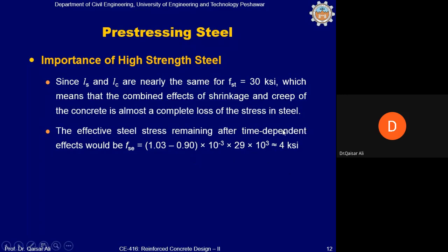तो हमें पता चल जाएगा कि हमारे पास फाइनली स्ट्रेस कितना रह गया। तो द फाइनल स्ट्रेस, the initial stress was 30 KSI, but after the creep and shrinkage reduction in the concrete member, the effective stress is 4 KSI. ठीक है, इनिशियली जो स्ट्रेस 30 KSI था वो आखिर में 4 KSI रह गया, क्योंकि जो स्टील में हमने स्ट्रेचिंग की थी वो स्ट्रेचिंग कंप्लीटली तकरीबन खत्म हो गई क्रीप और श्रिंकेज की वजह से,